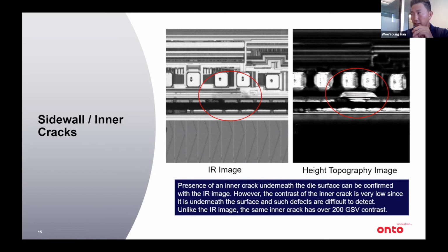But on the right side, we are looking at the same inner cracks, and this time we're showing images with a height topography based image. So, we have an image that is showing an intensity based topography, and as you can see, it can be very sensitive to slight changes of topography. And with that kind of image, we have a lot better chance of finding defects underneath the die surface.